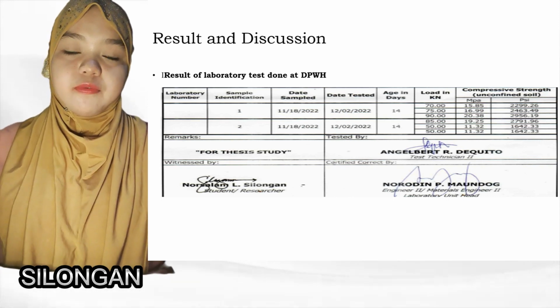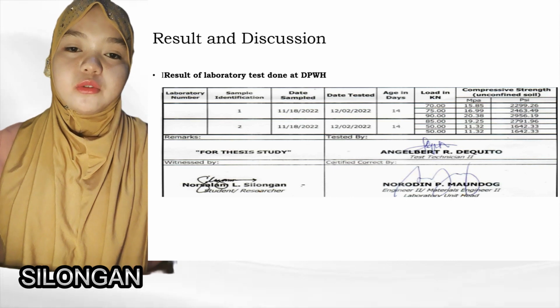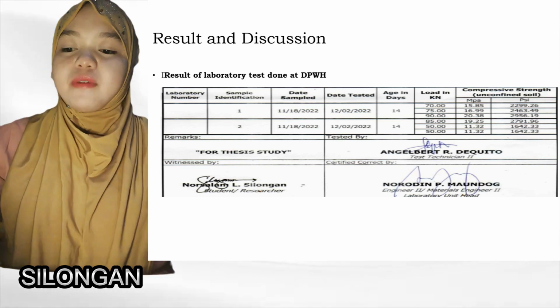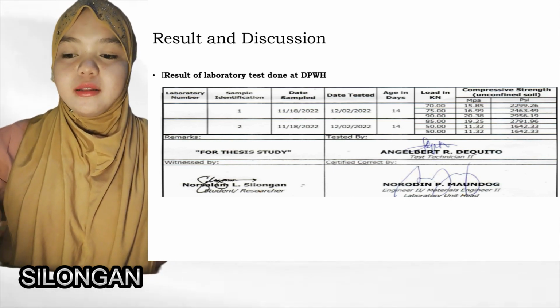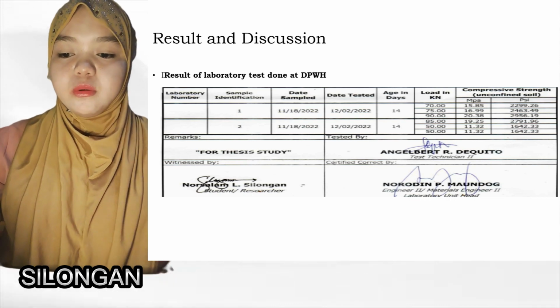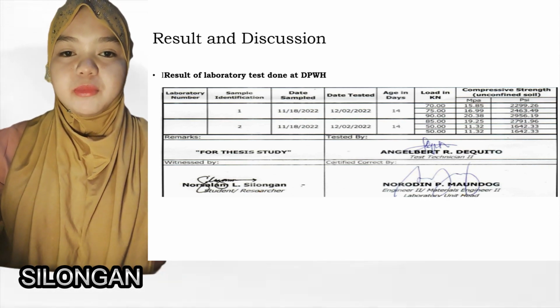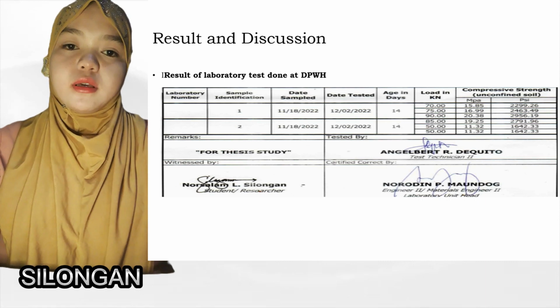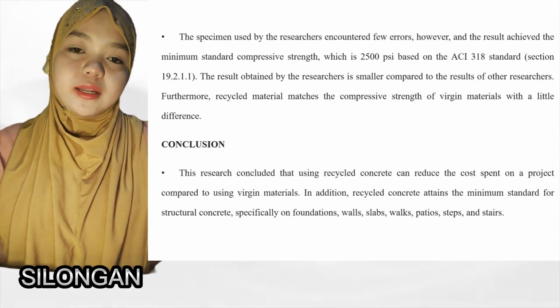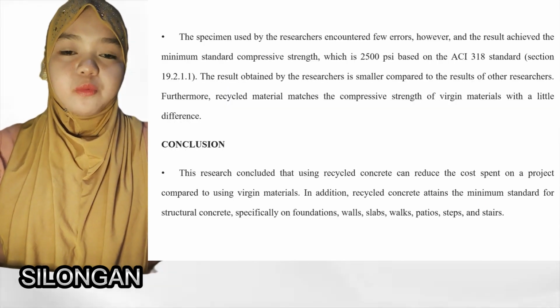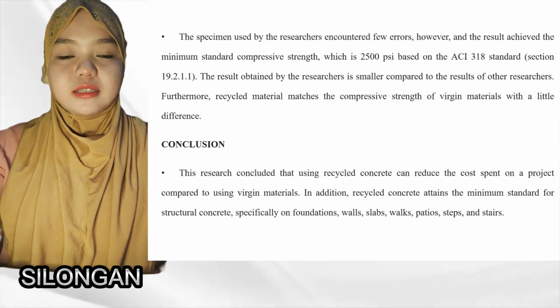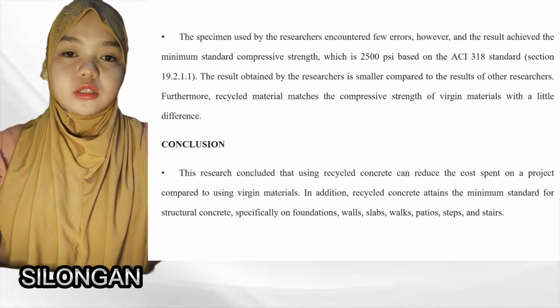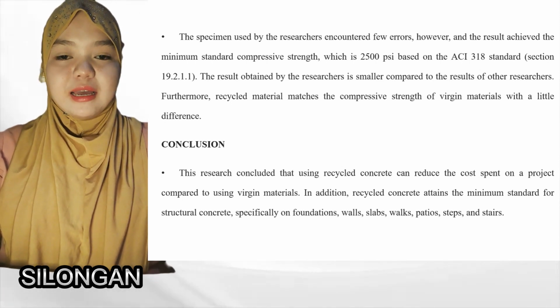The standard strength for compressive strength is 2,500 psi. From our test result, we gained 90 kilonewton or 2,956.19 psi. Even though we encountered many errors in creating our product, we still managed to attain the standard strength for compressive strength, which is 2,500 psi.